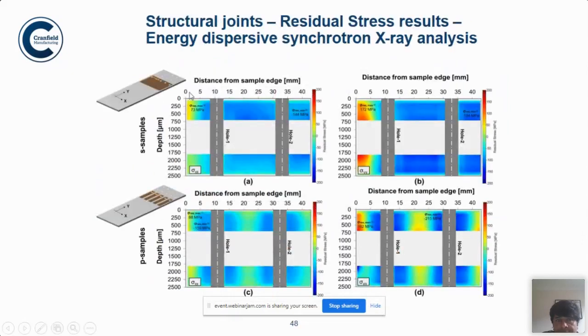This is my specific area of expertise. I use a lot of neutron and synchrotron in order to understand the stress state. As you can see here, the blue bit basically means compressive stress. Both the stripe and the patch configurations created tensile stresses. If you look carefully, because it is stripe, the entire thing is compressive along the whole of the length and the whole of the width, which is really not required, because it means the balancing tensile is forming somewhere here in the middle of the specimen.